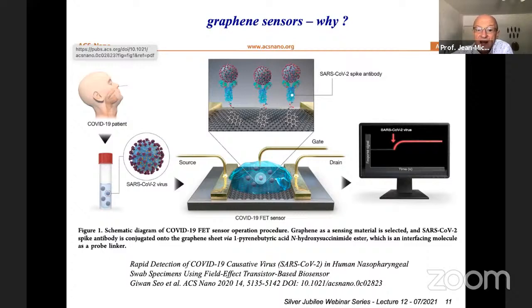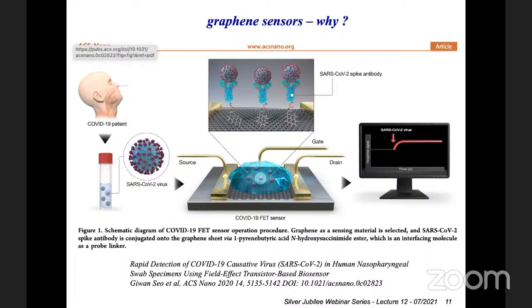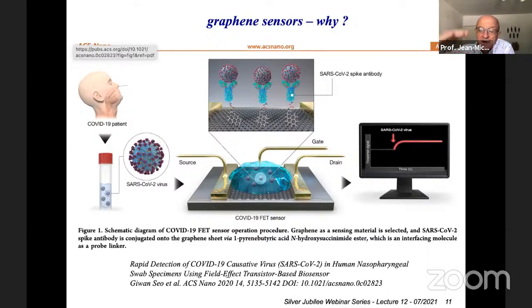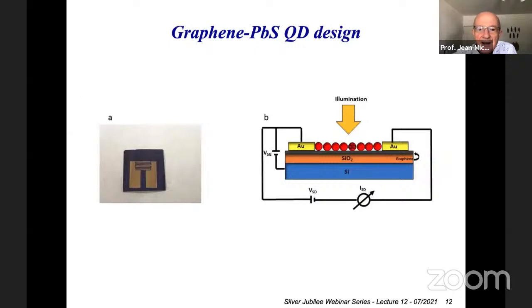You can do similar things for photo detection. The graphene doesn't absorb a lot of light. So in order to make a photo detector with graphene, we need light absorbers. And in a configuration similar to this one, the light absorber will create some electron hole pairs or excitons, which will change the interaction with the graphene and will shift the Fermi level of the graphene. The Fermi level of the graphene, again, is exactly located at the Dirac point, which is crossing between my two hands, where the energy is vertical and horizontally is a K vector, but it's a little bit different than the representation of energy I was showing previously. And you can make a photodetector.